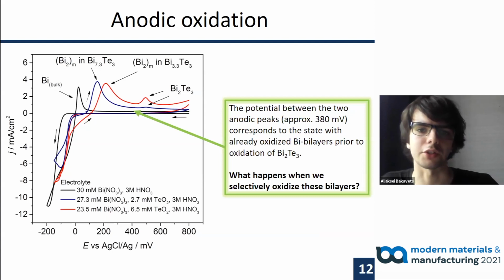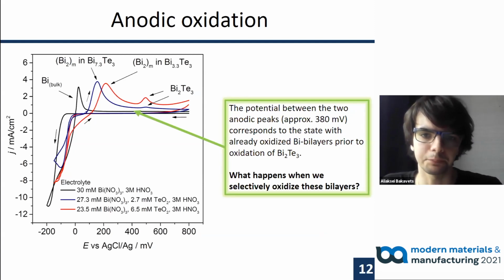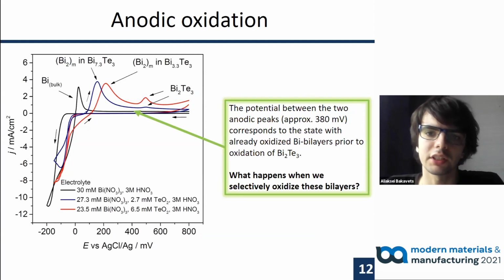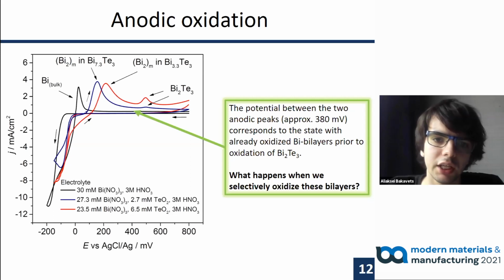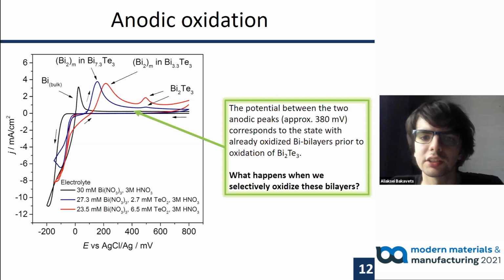Returning to cyclic voltammetry, what we see is that the anodic oxidation of bismuth bilayers proceeds well below the potential of Bi2Te3 anodic oxidation. And this gave us the idea to selectively oxidize those bismuth bilayers, leaving the crystal structure distorted.